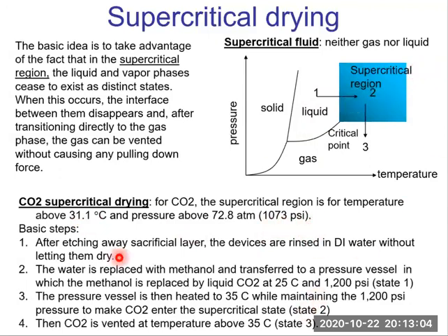So that's state one. Then the pressure vessel is heated to 35 Celsius while maintaining the 1200 PSI pressure to make CO2 enter the supercritical state, state two. We transit from state one to state two by increasing the temperature. The temperature now is 35 Celsius. The pressure is still 1200 PSI, so the pressure is constant.